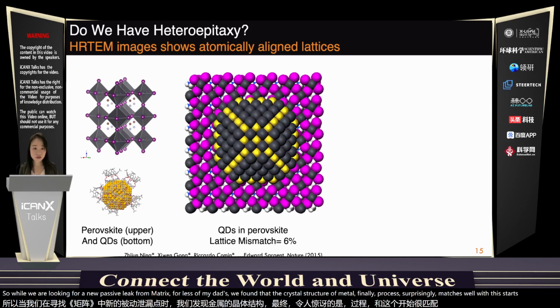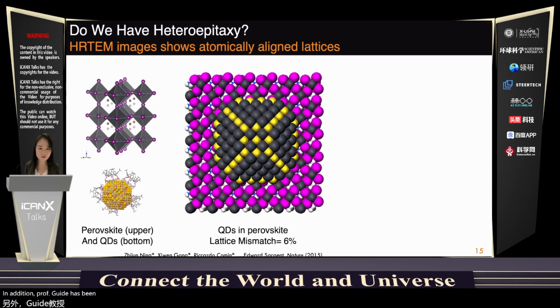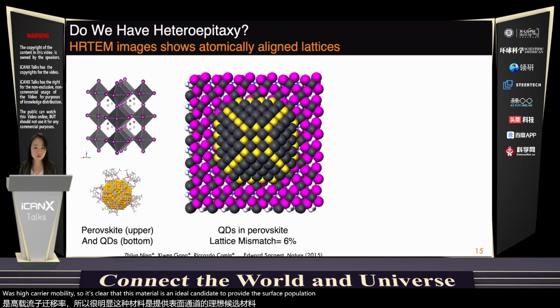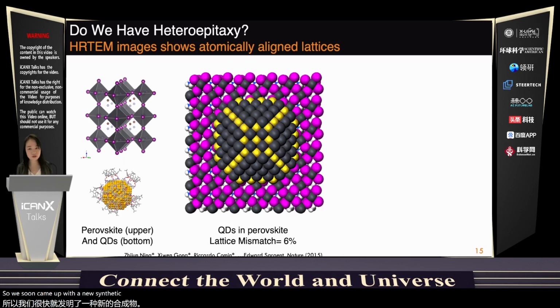In addition, perovskite is known for its excellent charge transport with high carrier mobility. So it's clear that this material is an ideal candidate to provide surface passivation to the quantum dots and enable excellent electronic transport. So we soon came up with a new synthetic method that successfully grows lead sulfide dots into the perovskite matrix. And then we asked ourselves, all right, they're now together, are these two materials aligned with each other at the atomic level, the way that we imagined?